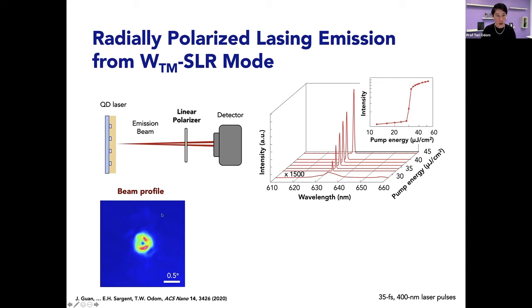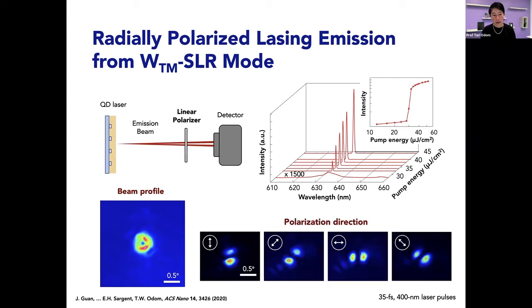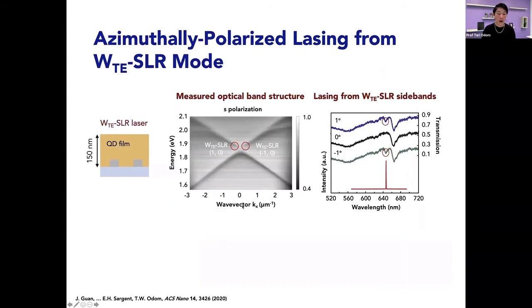And so we put a polarizer before the detector, and then we found that the intensity changed and the location of the spots rotated as we changed the polarization. And so we know from these polarization patterns that this is a radially polarized emission, which is quite interesting and quite nice.